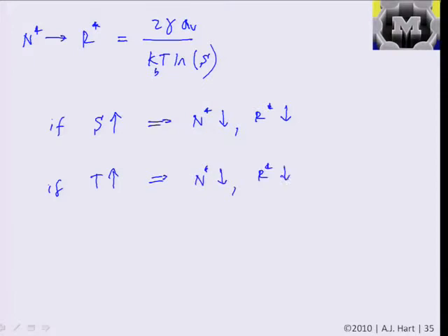So supersaturating the system and or increasing the amount of precursor is a way to initiate nucleation, is a way to cross this energetic threshold and start structures synthesizing. And ideally what we want to do is, for example, going back to the first picture, we want to start the process by adding that precursor, by rapidly increasing the temperature, and then once we form the nuclei, we want to step back into a regime where we already have clusters that are above the critical size, so they're not going to dissolve, but they still want to grow to decrease their free energy.